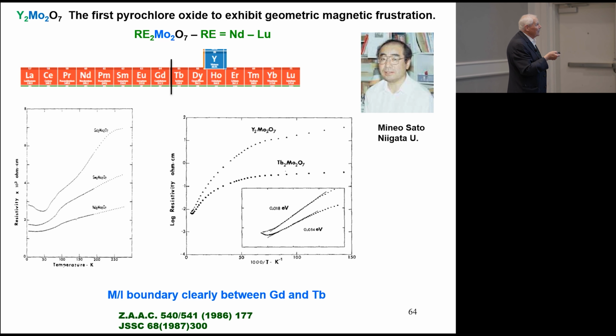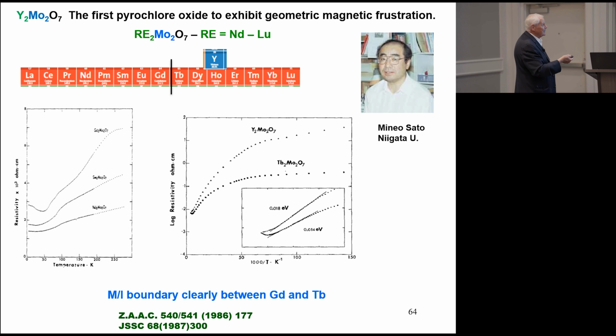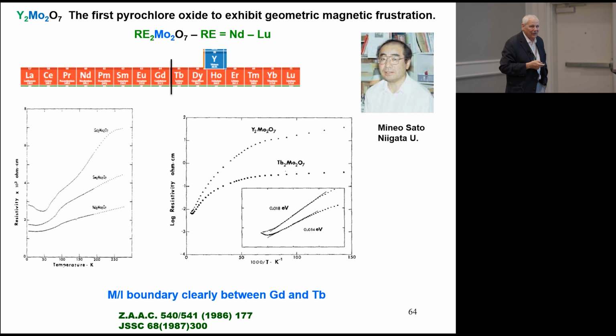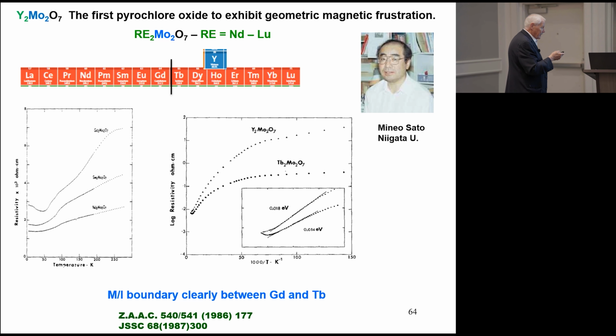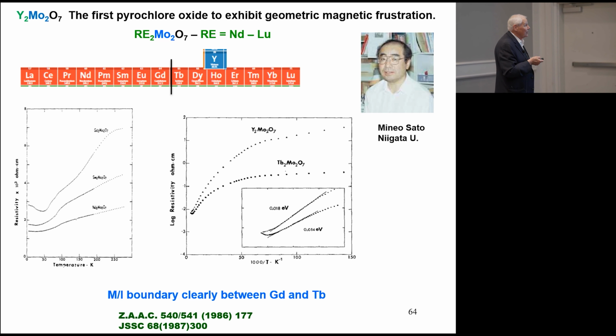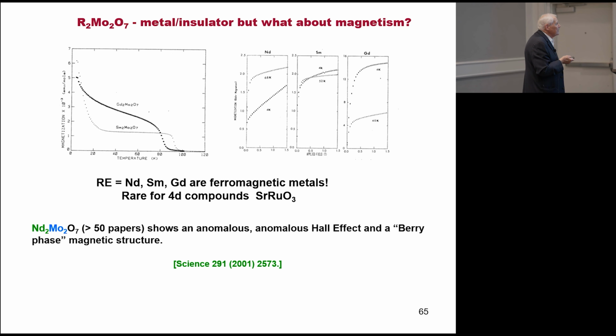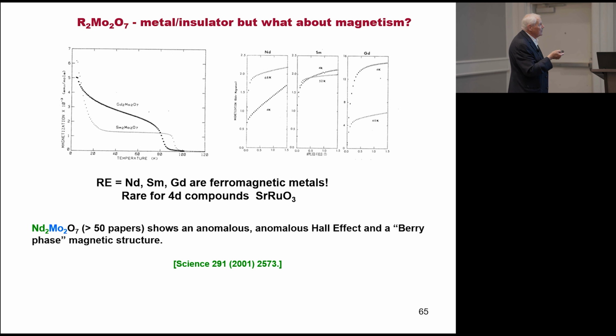This was in 1986. We made a remarkable discovery. I've included, by the way, that not everybody in the audience may have memorized that part of the periodic table. So here's the dividing line between gadolinium and terbium, their adjacent elements, and neodymium, samarium, and gadolinium are metals. These are resistivity curves. When you get to terbium, they're insulators. I've included yttrium, not in its expected place in the periodic table, but where it should be with respect to ionic radius. And so there's a clear metal-insulator boundary between gadolinium and terbium, which is a remarkable thing. And this work was done primarily by Mineo Sato of Niigata University, and he was visiting as a postdoc. Okay, just a couple of comments on the metals. There are ferromagnetic metals here with the magnetization curves. You've got almost perfect saturation.